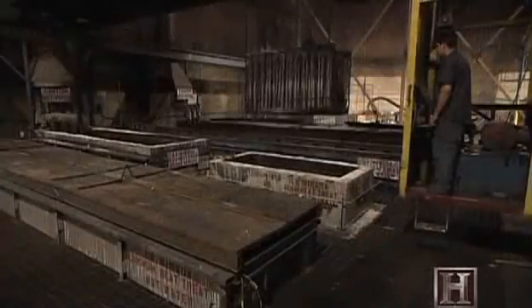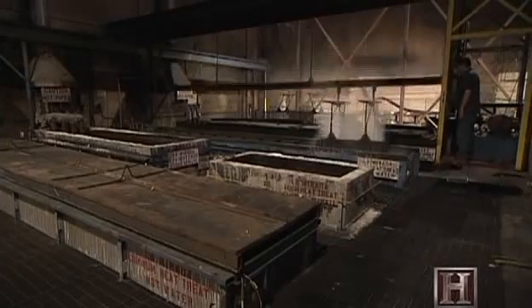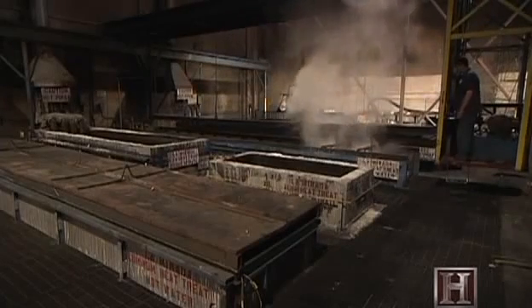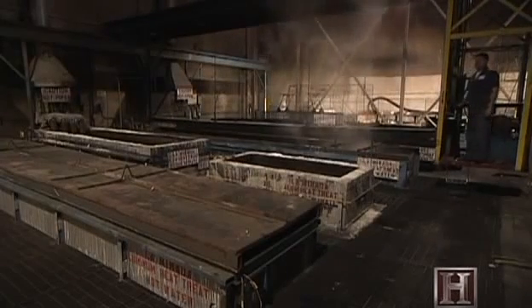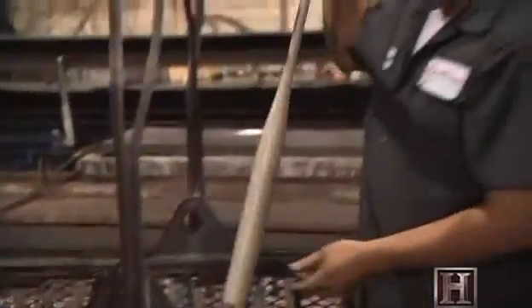Heat treat is a 2-step process. An elevated temperature for a certain amount of time, and then a rapid cooling called a quench. It's kind of exciting because you go from this salt bath to a water tank. You have to do it in less than 15 seconds. The rapid cooling following the elevated temperature soak creates microscopic particles in the aluminum, which strengthen the metal.